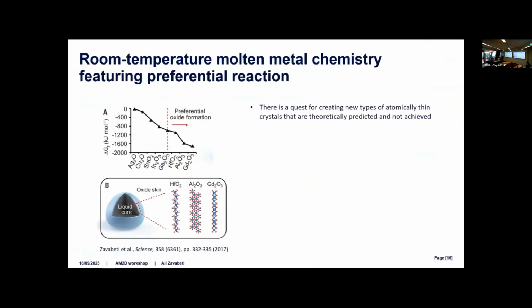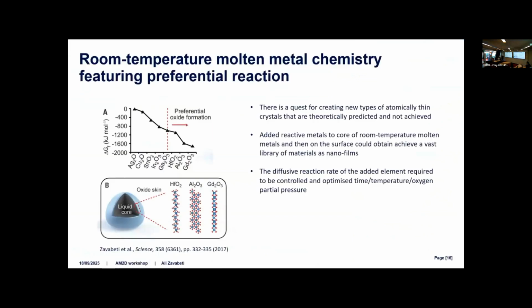So what we found out is that gallium can dissolve many metals. So we can very easily grind other powders into gallium, and therefore we can then harvest the oxide layer. We tried that with hafnium, aluminum, and gadolinium powders, and we could achieve a surface mostly dominated by these oxides. This is a different chemistry, and the way we harvest is a touch printing method. So we don't do squeeze printing.